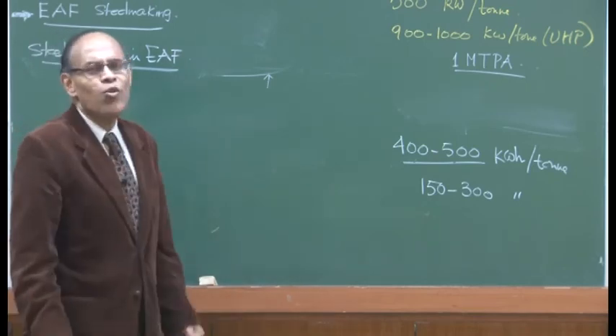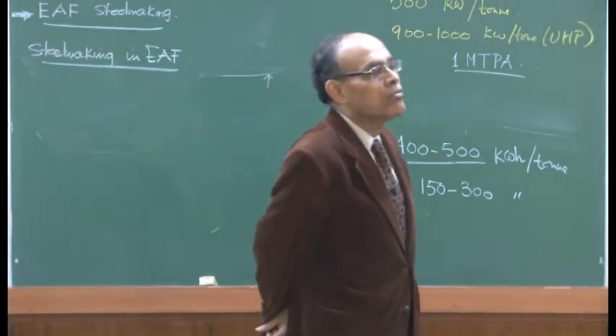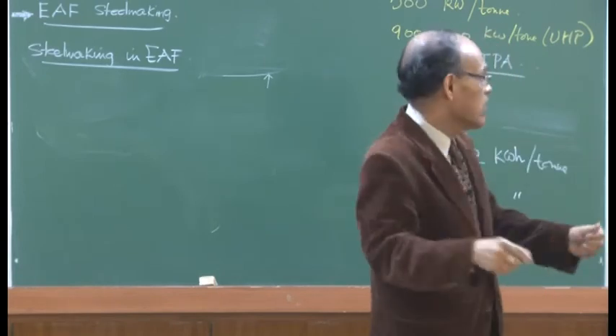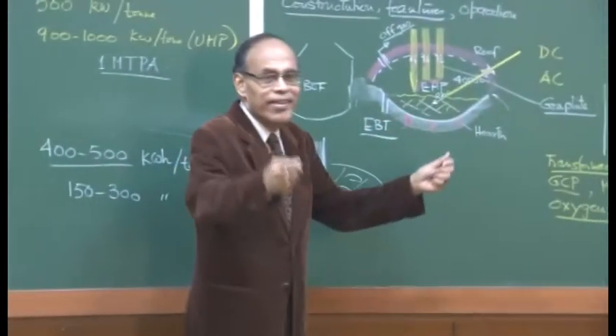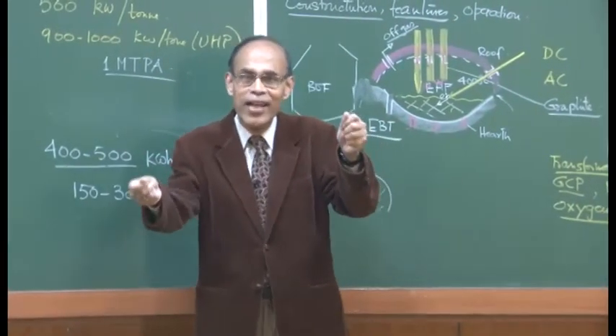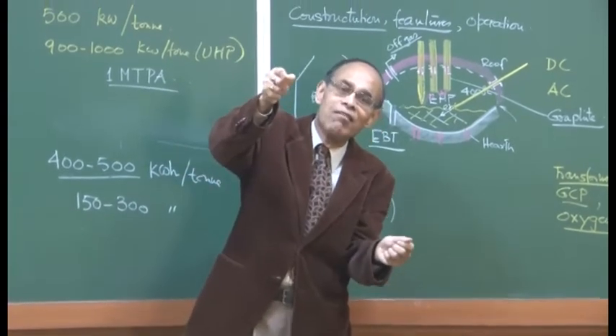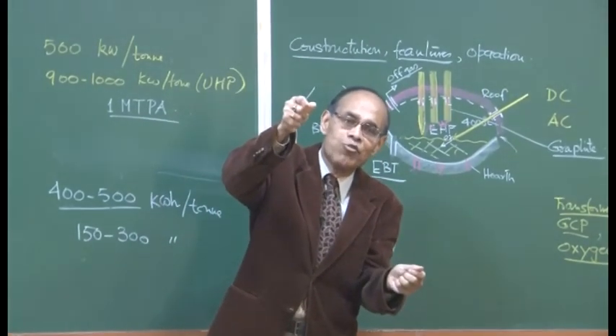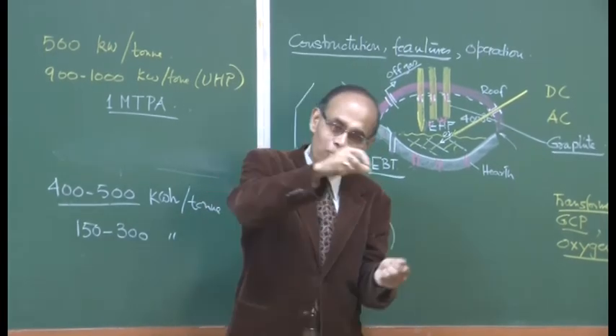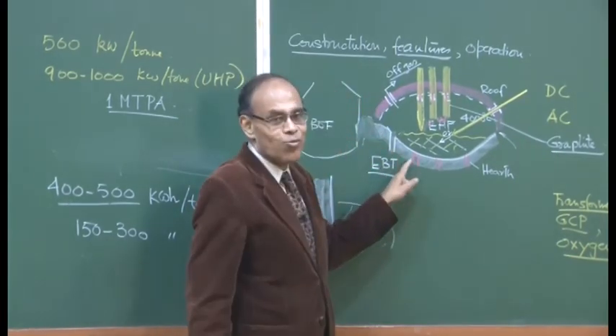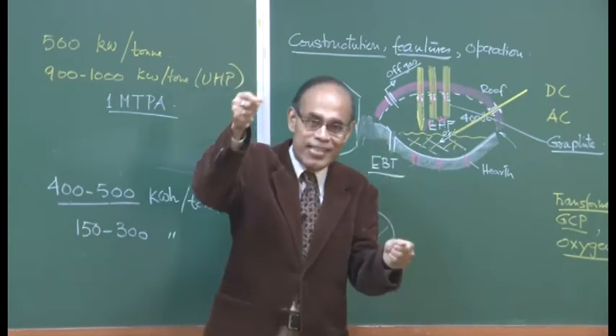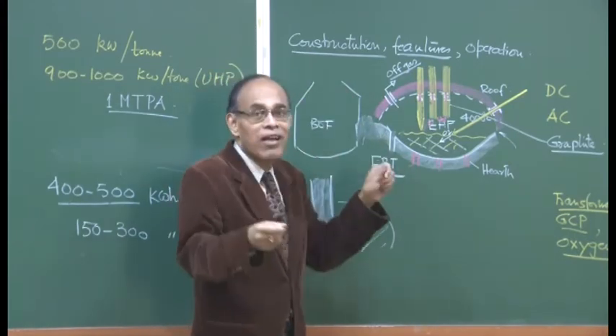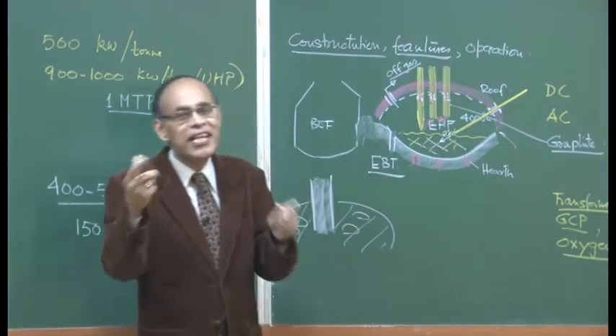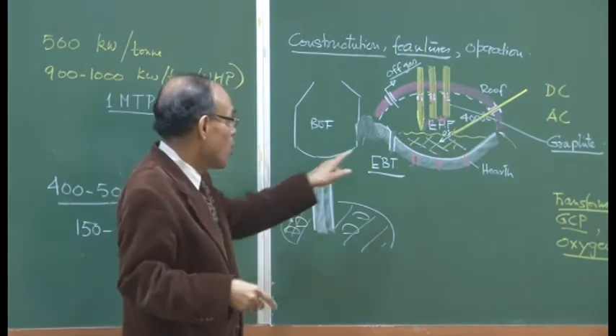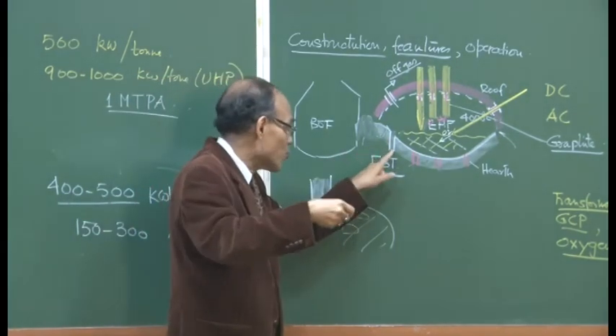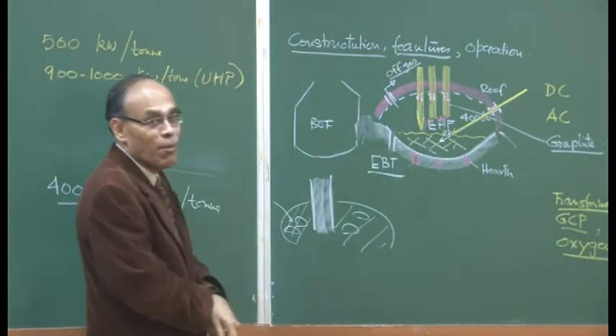The heat preparation is more or less the same, that once you make a steel, these furnaces, by the by, while the BOF converter can be tilted almost by 70 to 75 degrees in order to tap the molten metal, these furnaces are not tiltable to that extent. Okay? They can be tilted for example by 8 degrees, 10 degrees, or at the most 18 degrees or so, because to drain out the molten metal through this eccentric bottom tapping facility.